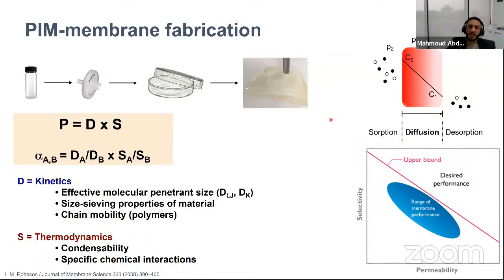The mechanism of gas separation is very simple. It has three stages: sorption, diffusion, and desorption. Imagine this red box is your membrane, and you have, let's say, carbon dioxide and methane on this side. This mixture of gases will approach the surface of the membrane by applied pressure, get absorbed on the surface, and then diffuse through the membrane to come out from the other side. And from the other side, you will see that some gases are favored over others. For example, CO2 will go faster than methane.